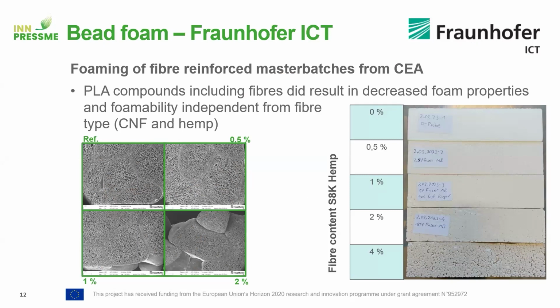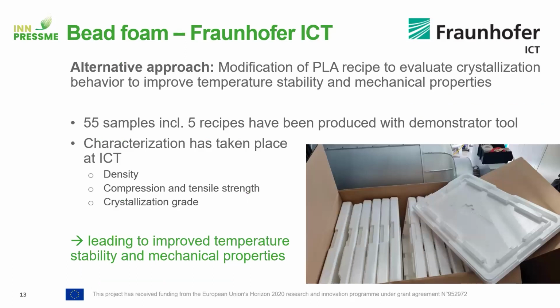Then coming to foaming, we at Fraunhofer ICT did various tests with the fiber reinforced materials. But what we saw is that the incorporation of such fibers more or less hindered the foaming, or at least decreased the foamability of the materials. You can see this on the right image, where the more fiber we had inside the foam, the less good is the foam quality. So in the end, we decided to not go on with the fiber reinforcement, and we went with an alternative approach to improve the properties of the PLA bead foams.